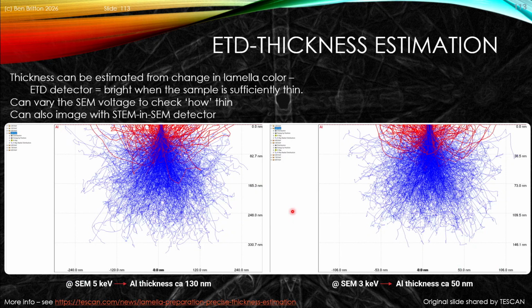Other methods that you can use, and there's a description of this on the Tescan website that talks about lamella preparation, you can exploit the electron transparency and contrast. So the thickness can be estimated from the change in lamella color. You use the ETD detector and the sample goes bright when the sample is sufficiently thin. When you then change the voltage, it changes the interaction depths of the secondary and backscatter electrons. And as we see here, we change from 5 kV to 3 kV. We can see that this scale is changing quite significantly. And that enables us to estimate that when the contribution of backscatter starts to decrease very significantly, that can tell us about the thickness of the foil to give us a good estimate of this thickness that could be calibrated via other methods. We can also, of course, image using a 30 kV STEM detector to see whether the contrast that we're interested in starts to appear nicely.